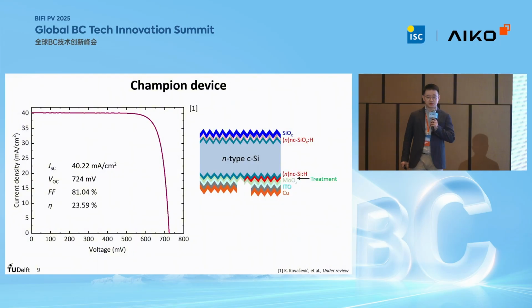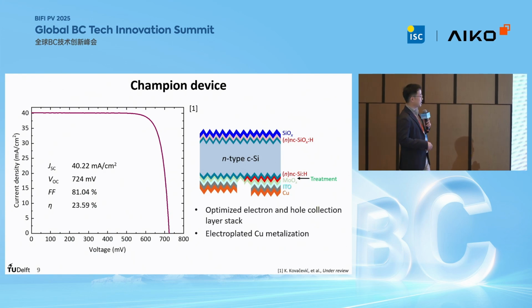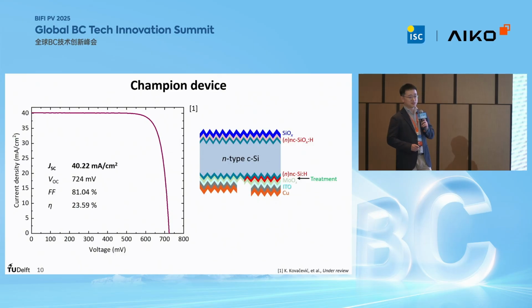Last year in Zhuhai, I presented such a device with an efficiency of 21%. After some optimization by the student this year, we could achieve an efficiency jump of 2% absolute to 23.59%, with a relatively good VOC because we are using a 280 micrometer thick float zone wafer. This device also features a copper-plated electrode. But as you can see, the JSC of such a device is still quite below the state-of-the-art back-contact solar cells.